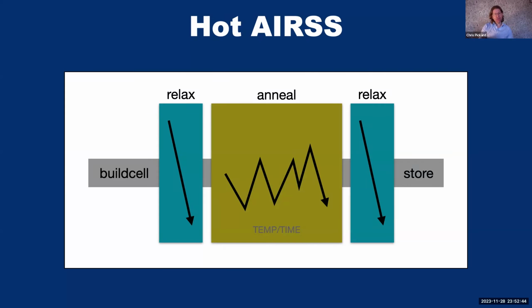Now, from the point of view of random structure search, the results that we output are relaxed structures. And this is in some ways just thought of as a more complicated optimization algorithm, but it's physically motivated, especially as now in a metallurgy department, I can see the importance of annealing. In some ways, it makes random structure search a bit more like simulated annealing. Okay, but it's not exactly the same as simulated annealing. It's kind of the same as doing lots and lots of independent molecular dynamics simulations.